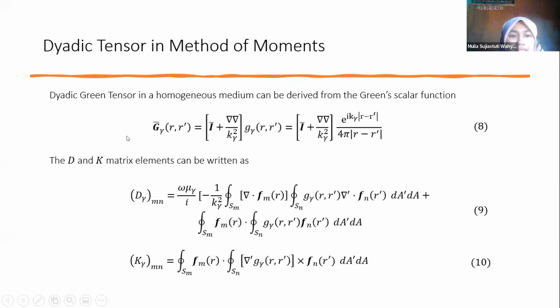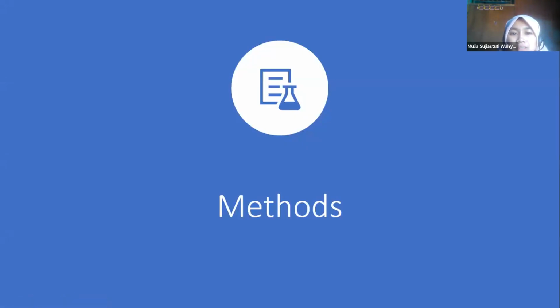Okay, there is the dyadic Green tensor. The dyadic Green tensor in a homogeneous medium can be derived from the scalar Green function. If we know the dyadic Green tensor, we can find the D and K matrices in the A matrix, and then we can substitute D and K in the A matrix and find the surface current densities. And if we get the surface current densities, we substitute them again into equations 1 and 2, and we can find the complete electric field and magnetic field integral equation. Okay, there is the method that I use in this research.